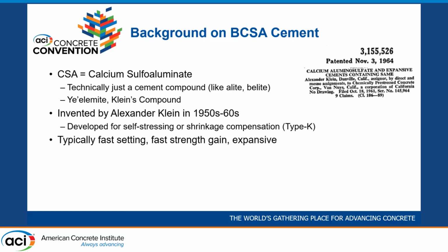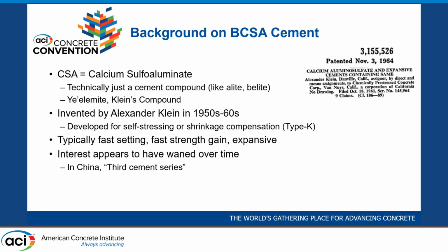A lot of CSA cements tend to be faster setting, have faster strength gain. They can tend to be expansive, but again, it all depends on the composition of the particular cement, how much CSA it has in it. Initially, these cements were quite popular, it seems, in the 60s and 70s. The popularity kind of waned over time in the United States, but there's some more interest because of its environmental friendliness now. But in China, it's been used on a very wide scale for a long time. CSA cements are known as the third cement series there.